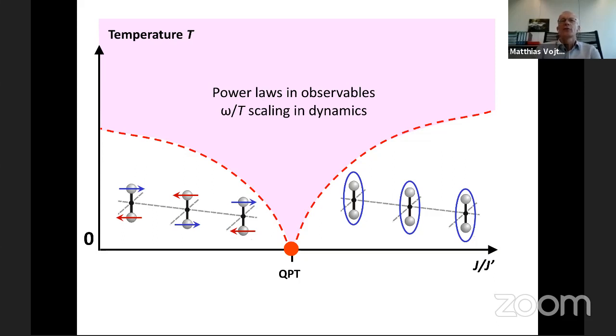There is an interesting idea to put ruthenium chloride, which some of you may know is a van der Waals material like graphene, so you can scotch tape it to get a single layer. So people have put this on graphene. There is an experimental paper published which has ruthenium chloride on graphene. And one idea being that with charge transfer, you may metallize ruthenium chloride. This in principle works, but the problem, so there is charge transfer. But what you also do is you make the graphene metallic, because if you charge transfer, graphene is no longer charge neutral. And then it's difficult to separate the conduction of the graphene from the conduction of your doped ruthenium chloride. And therefore, nothing which is reliable in terms of answering the question has been achieved. But these are the attempts. And so the honest answer is no, but I would not give up hope.